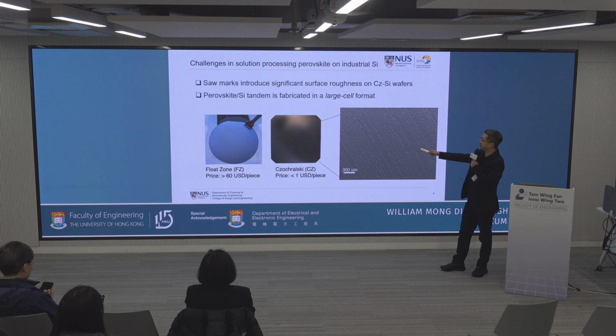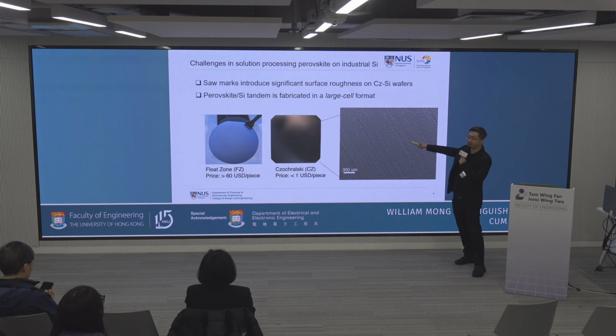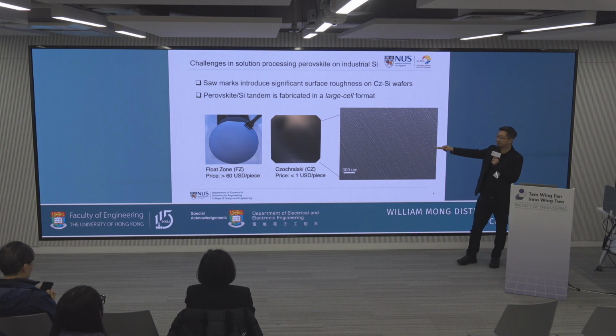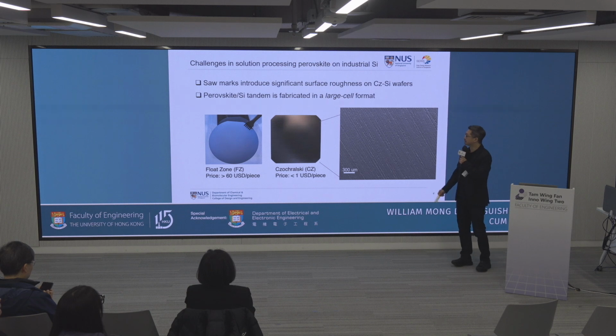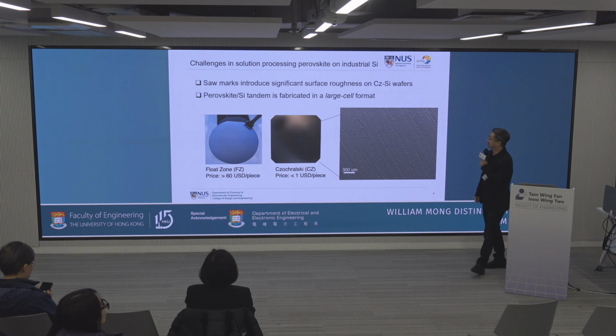But the big challenge is if you use a CZ wafer, it's a very rough wafer compared with this atomically flat float zone wafer. So you need to figure out how to deposit high quality perovskite on this very rough surface and to get a very efficient and stable perovskite silicon tandem, and in large scale.